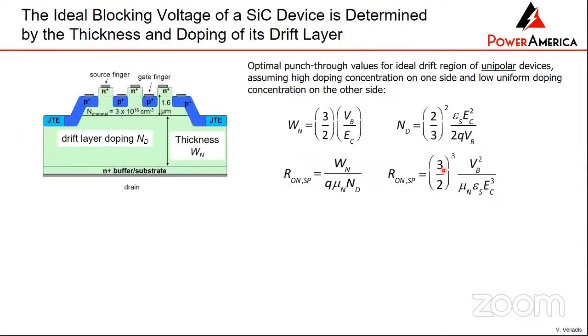And again, for vertical devices, where silicon carbide devices are almost all vertical, you can see that the amount of voltage that the device can hold has to do with the thickness of this layer and the doping of these layers. And the equations here give you the optimal conditions. So suppose you want to make a device that will do 1,000 volts. You put 1,000 volts here, you put the critical electric field of silicon carbide. This will tell you the thickness of this layer and the resistance that you're going to have.